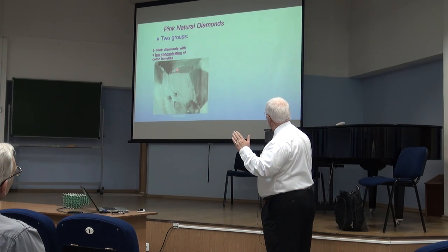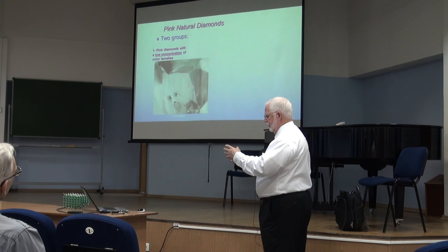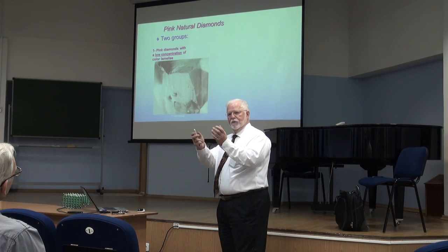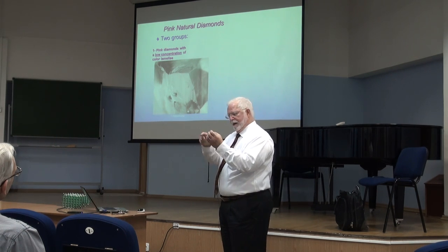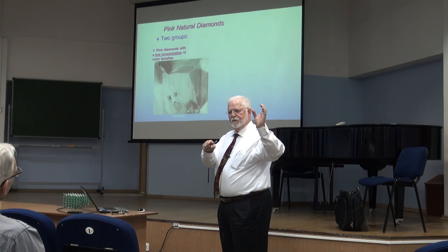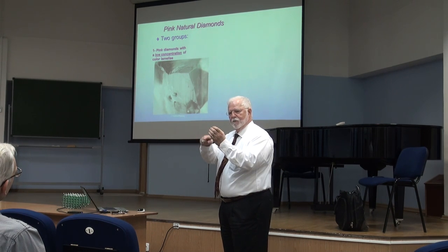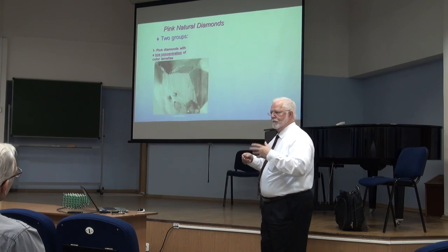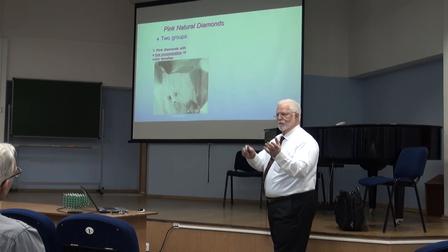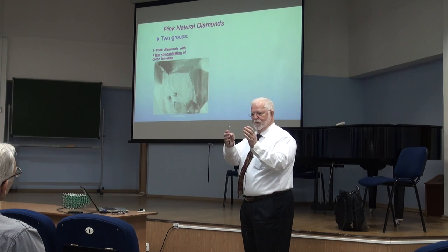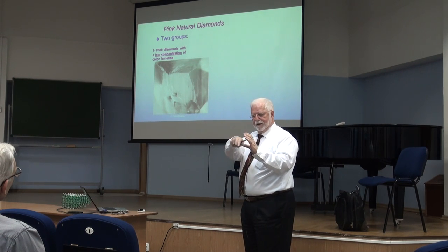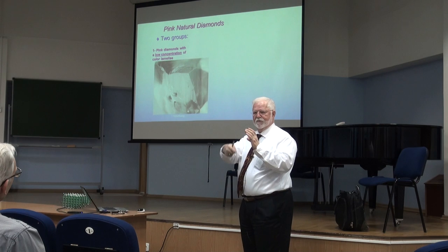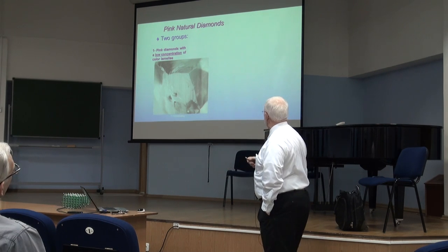And I've actually had a rough diamond, it wasn't very large, that looked pink when you held it in your hands, and I laser cut off one corner just so I could polish a face on it. The whole diamond went white because the pink color was all localized in one lamella down in that corner. And so when you're making a pink gemstone, what the cutters do is they rotate the stone so you can't see the lamella. Your eye visually has to look at light that goes through these lamella and come out, so the whole stone looks pink.